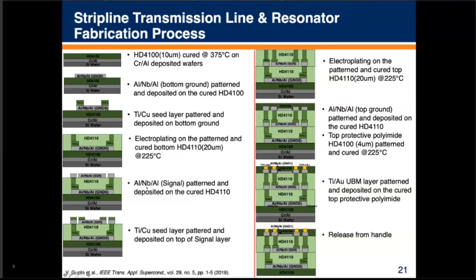So for those of you that aren't aware, niobium sometimes forms kind of a columnar or porous type of structure. And in that case, when you try to cure polyimide on top of it, there's the potential for some of those chemicals that come out of the curing process to get down into the niobium and cause the superconducting properties to be degraded, or at least in some cases significantly degraded to the point where it's just not a superconductor anymore. If we use a thin layer of aluminum before and after that, then we found that we can cure the polyimide up to reasonably high temperatures and get good mechanical properties and good dielectric properties. That was actually something we spent quite a bit of time on, looking at different barrier layers for those signal layers to be able to do the multi-layer process.